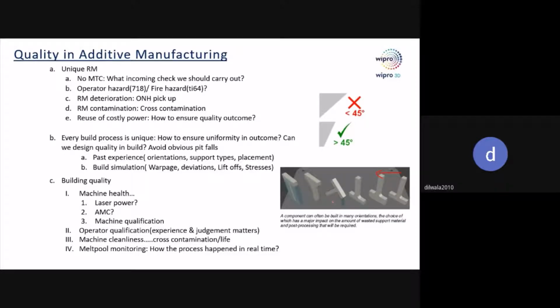I can tilt it at an angle. You can see this, right? It's not perpendicular. He has tilted it at an angle. You need to see that. Can you tilt at an angle in this way, or can you put it in some other orientation so that it does not come perpendicular to the recoater? If it is perpendicular to the recoater, there is a possibility that it will try to lift off the component from the already built layer.